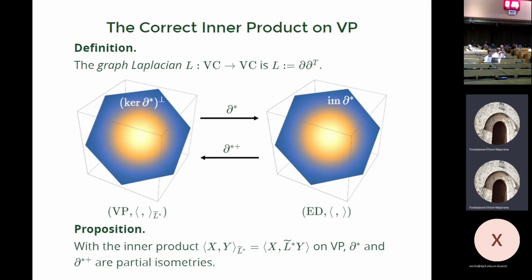So this is really why the graph Laplacian shows up in phantom network theory, and the slide I showed you earlier is exactly because of this phenomenon. The tilde is to deal with the fact that this thing has a kernel, and we don't like that. So the L tilde fixes the kernel, to make this an honest inner product and not a degenerate inner product. But basically, the graph Laplacian is showing up here.